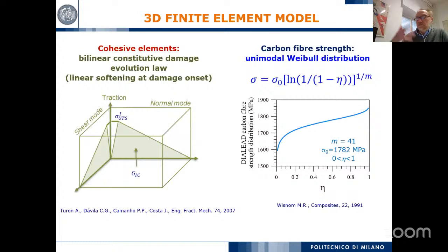In terms of detail, I don't want to go into the cohesive element damage evolution. That is quite standard. I just want to mention that we also introduce the variability of the carbon fiber strength using a Weibull distribution. This allows us to change the strength of the fiber, which is very well known, assuming this distribution, and so we can create a variation of strength inside the ply and along the length of the ply. This is interesting and important because this happens in the real material.